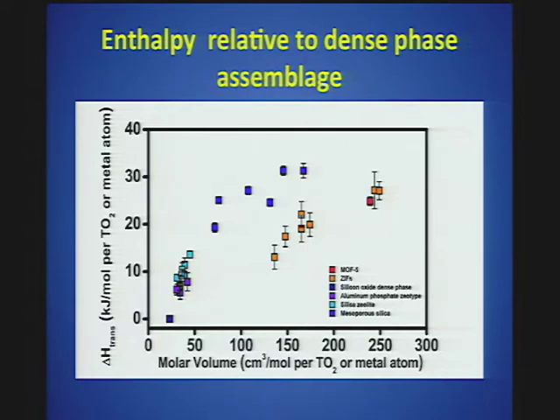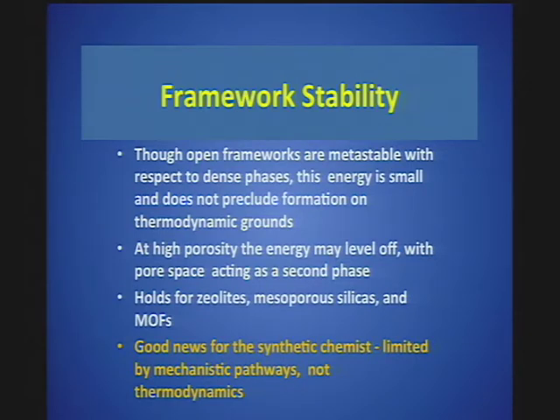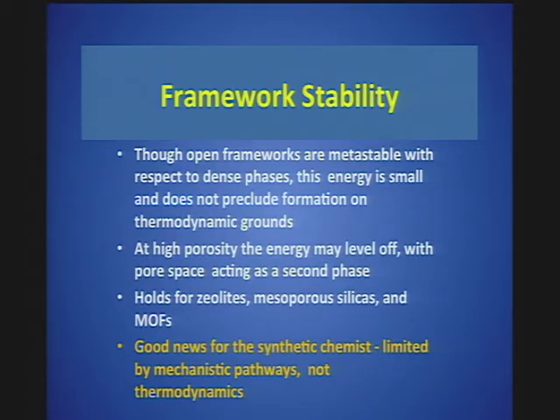What the thermochemical data show is that the role of these structure-directing agents is more in the selection of particular structures rather than in the stabilization of one structure relative to another. The general conclusions we can draw are that there are many structures of the same or relatively the same energetics, that they form a dense energy landscape, and that the ones you make depend really on the cleverness of your synthetic pathway. This was good news for the zeolite synthesis people back in the mid-1990s, and perhaps finding these small energy differences really empowered them to get together with organic chemists and ask: if we make a specific structure-directing agent, what is the mechanism for making the structure? So my earlier comments on stability versus persistence — kinetic versus thermodynamic factors — really emanate from this point of view.